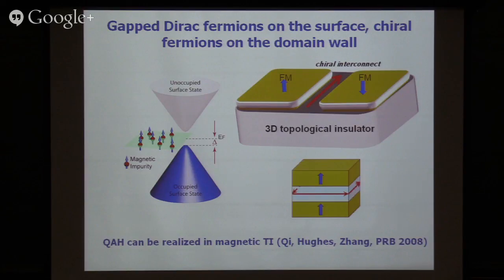But there's actually one interesting thing that people tend to overlook. That's if you have a magnetic moment on the surface, magnetic moments can have a domain, right? So then if I have this region spin up, but another region spin down, again, this becomes an interesting kind of twist. Because then on the interface, on the domain wall, you would expect there's no gap. But not only is there no gap, it has an exact chiral sense.